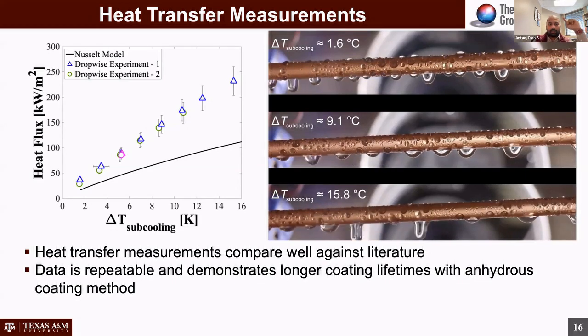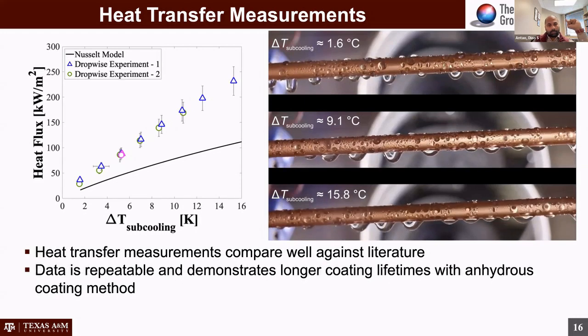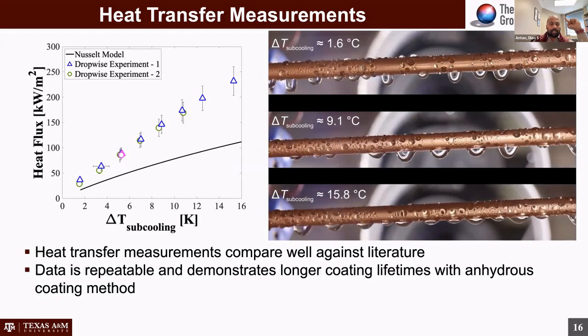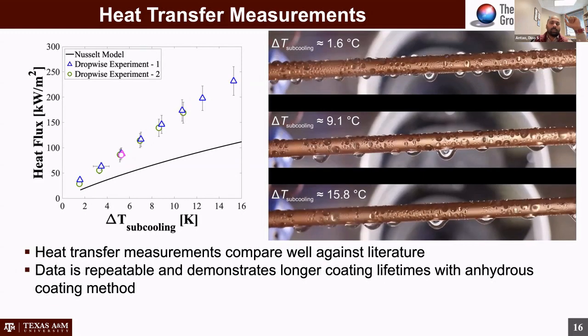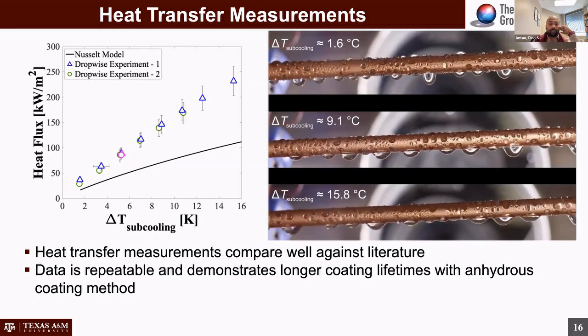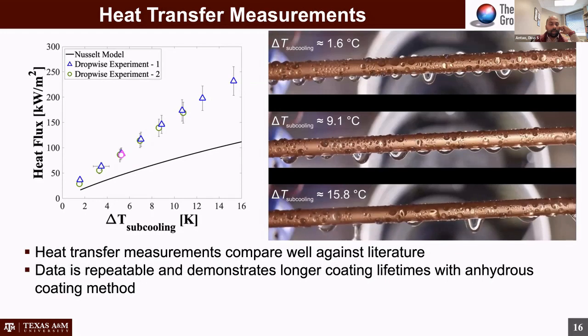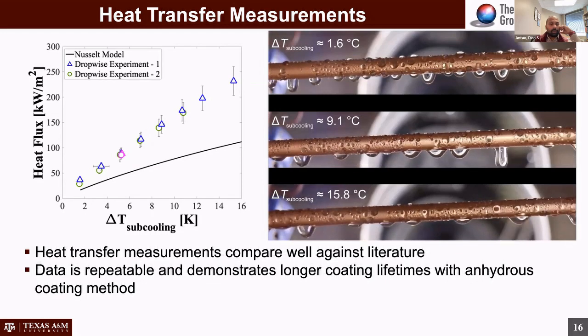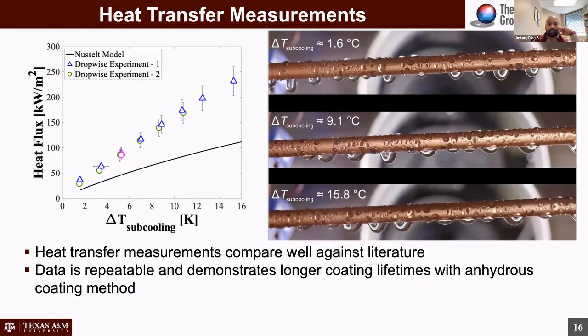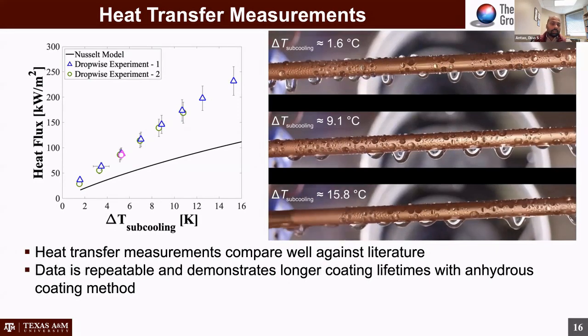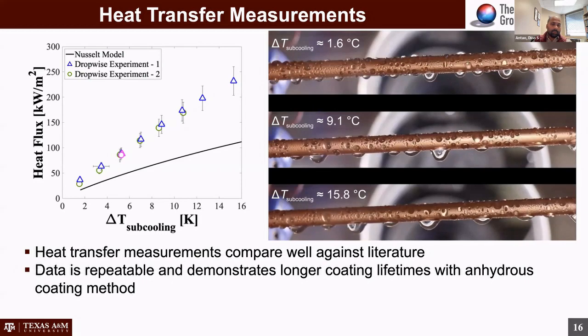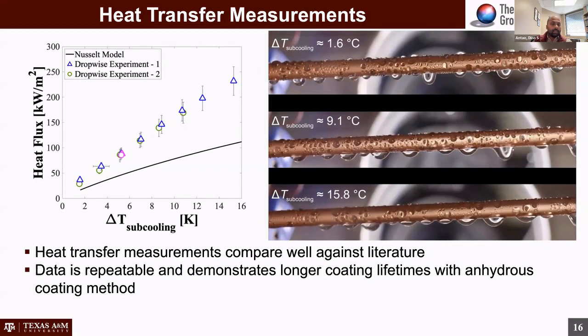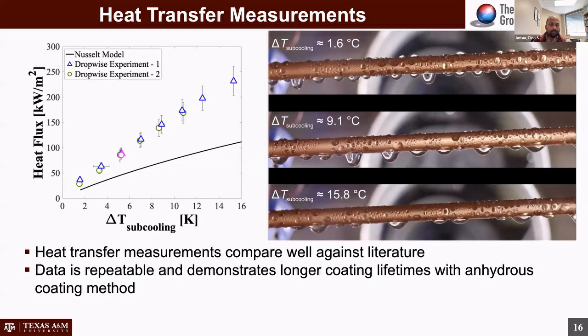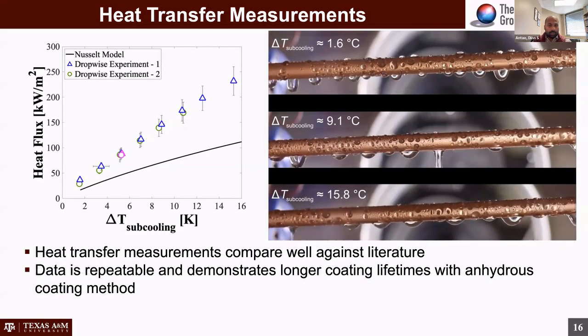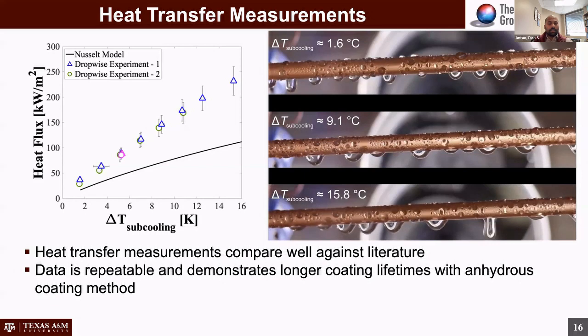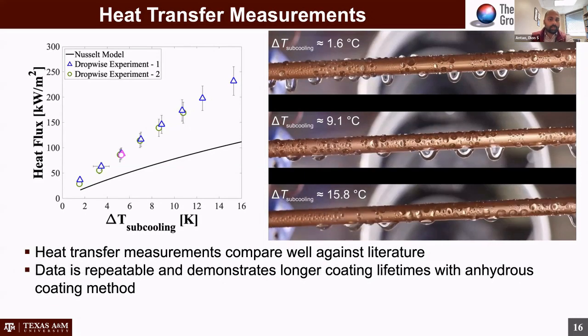One is our system is fairly clean in terms of presence of non-condensables. So in that 4 or 5 hours, we did not accumulate sufficient amount of non-condensables to affect the experiment. And this is important because even 1 or 2 Pascal of non-condensables can really affect condensation performance. The other thing it told us was if the performance is the same at the start and at the end, most likely the coating itself has not failed. And so it validates this approach to doing coatings in this anhydrous environment and with this oxygen plasma chemistry.